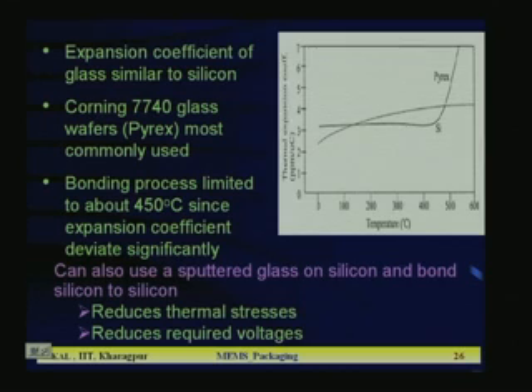For that I can show you a plot of the temperature versus thermal expansion coefficient. You can see here up to a certain temperature, 450 degrees C, for silicon and Pyrex the thermal expansion coefficient is almost similar. Corning glass 7740 wafer, which is most commonly used, a little bit conducting, this particular Corning glass number, Pyrex, is used for most of the glass silicon bonding in MEMS, because there we find a good matching between the thermal expansion coefficients of the two materials. Bonding process is limited to about 450 degrees C, since expansion coefficients deviate significantly after 450 degrees C. You can see here the two curves deviate further if you go on increasing the temperature.